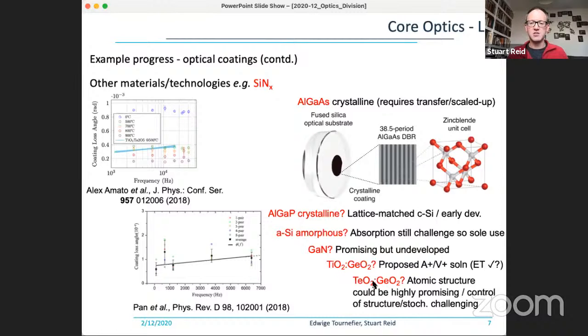And there are the various oxides that the atomic simulation work has been proposing could be attractive for ET-HF, such as titania germania, which is currently the most likely high index material for A+ and perhaps for V+. And there are other oxides such as tellurium, which look attractive in terms of this corner sharing network.